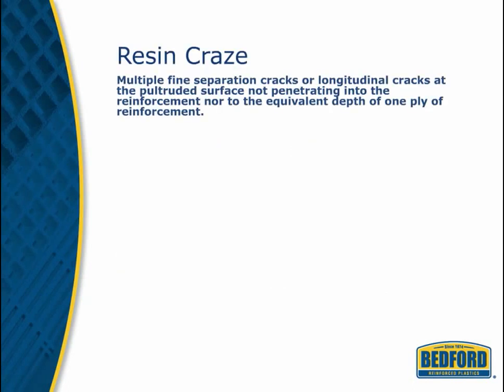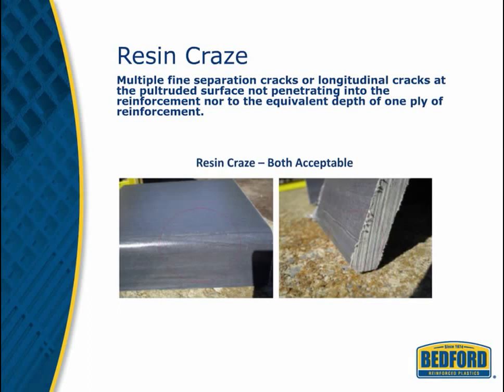Resin craze is when multiple fine separation cracks or longitudinal cracks occur on the pultruded surface. These cracks are acceptable over the entire length of the part as long as they do not penetrate into the reinforcement nor to the depth of one ply of reinforcement.